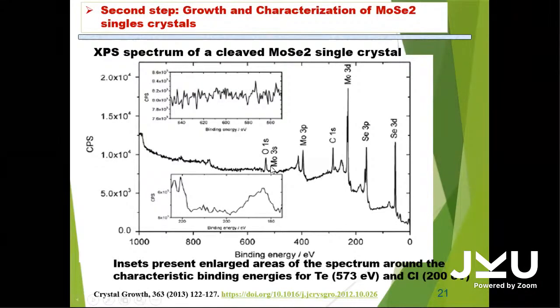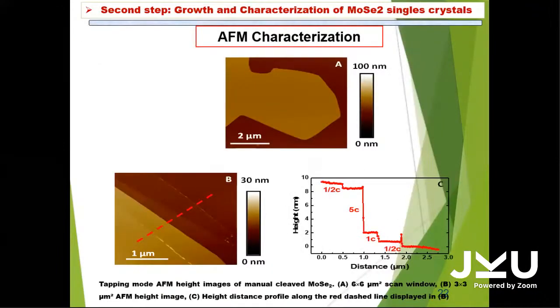We also have peaks of oxygen and carbon, but they can be removed by manual cleave. Growth by layering of lamellar structure is clearly demonstrated by AFM analysis, which was also used for the material characterization. The value of the C parameter is in perfect agreement with its earlier result.